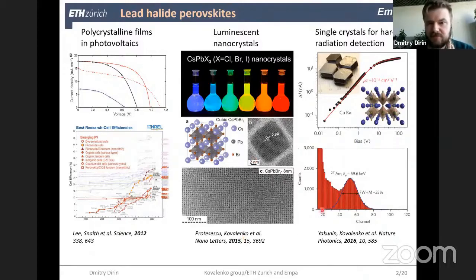And then a bit later, again in our group, we tried to approach the study of those materials from a very different angle. Instead of making colloidal nanoparticles, we tried to grow bulk single crystals of those materials via a solution process. And we have shown that those materials can be very interesting for hard radiation detection. There are many other fields of applications where those materials now show good performance.